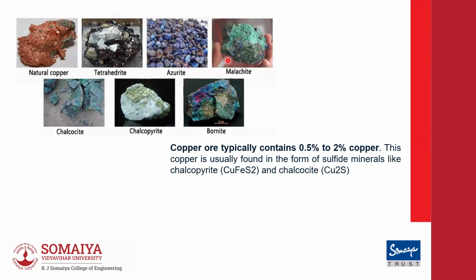Now, how is copper produced? These are my different ores of copper. Just to give you one perspective, when I say ore in iron and steel making, when I say iron ore, it is iron oxide. If I take a natural rock, I would have some amount of iron oxide there, maybe 5%, 10%. But then what is the workable limit for iron oxide if I'm talking about iron and steel? Usually, if it's a really good ore, anything above 62 is probably one of the best ores you can get. Nowadays, people are working with 58% iron oxide, which means the remaining 42% is gangue, and you don't want it.